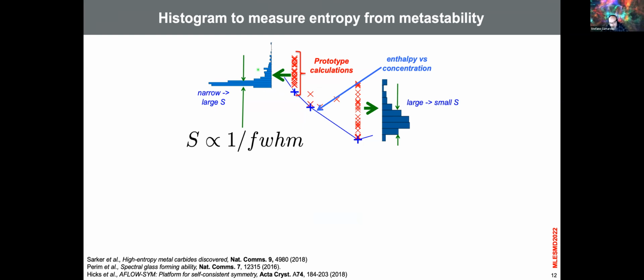So we call this entropy forming ability and not really entropy. The entropy forming ability is really defined as the thermodynamic density of states, similar to the electronic density of states. You have accumulation of these objects, and if the peak is narrow, then you have a lot of entropy. If the peak is broad, then you have a very low entropy.